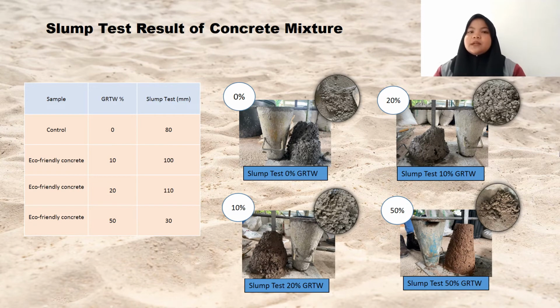For control sample, the slump fall is 80 mm. For 10% and 20%, the slump fall value is 100 and 110 mm. For 50%, the slump fall is 30 mm. According to BS standard, 50% of GRTW was out of the range because the range is between 60 to 180 mm.